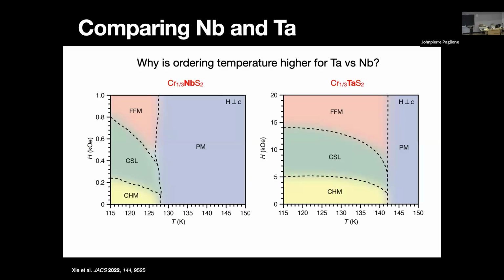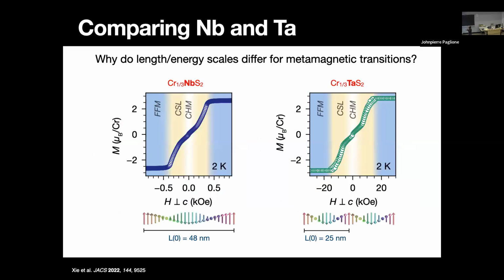So when we look at the chromium intercalated niobium and tantalum disulfides, we can ask the question why these have qualitatively very similar phase diagrams, but the ordering temperature for the tantalum analog is higher by a shade than that of the niobium, but otherwise they are really similar. And so we can use these two systems to compare and try to see what we learn about the magnetic exchange here. And we can also learn something about the D term in these materials, because for the niobium analog, the wavelength of that helimagnetic winding is about 50 nanometers, and it's half that in the tantalum. Okay, so the tantalum analog seems to have a much stronger Dzyaloshinskii-Moriya interaction, as we might expect.